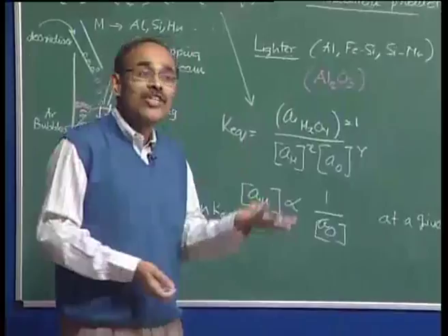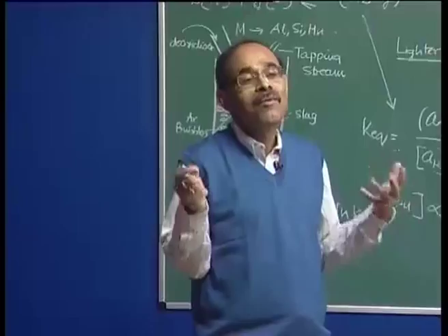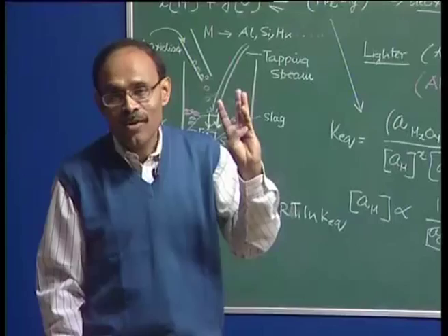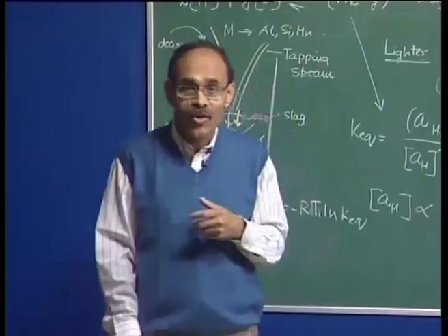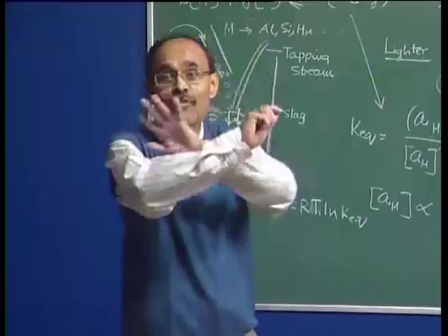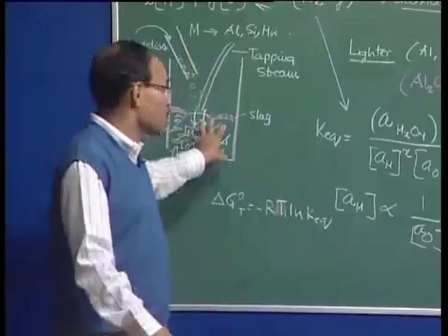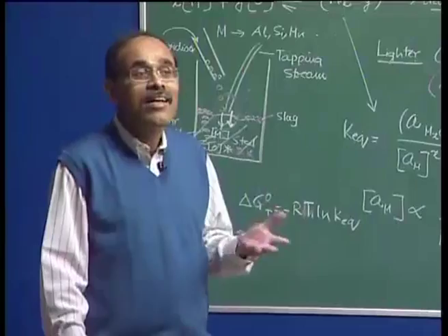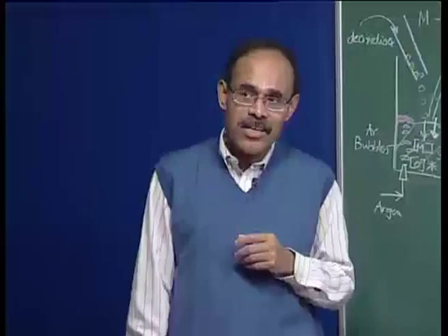We have solid deoxidation product, liquid deoxidation product, and gaseous deoxidation product. Solid is not wanted as far as possible, but aluminum, which is such a powerful deoxidizer, which gives low residual and can bring down oxygen to a very low level with only a little contamination, unfortunately forms a solid deoxidation product. We want the final steel to be devoid of these deoxidation products, which we will later call inclusions. Contamination of steel with deoxidation product is referred to as dirty steel, and the associated subject is cleanliness control and so on.